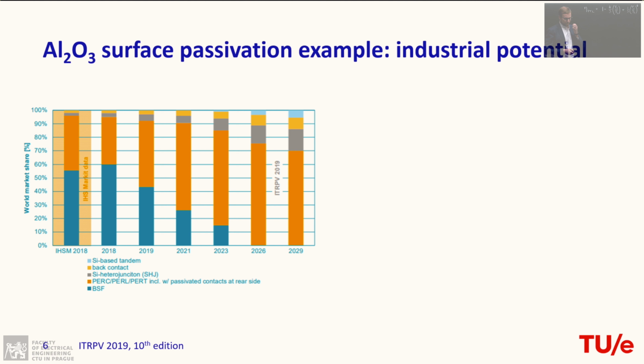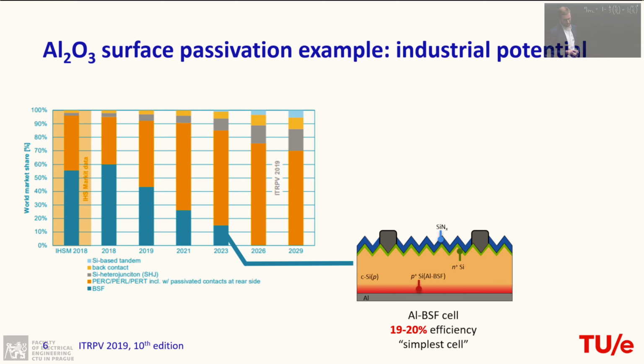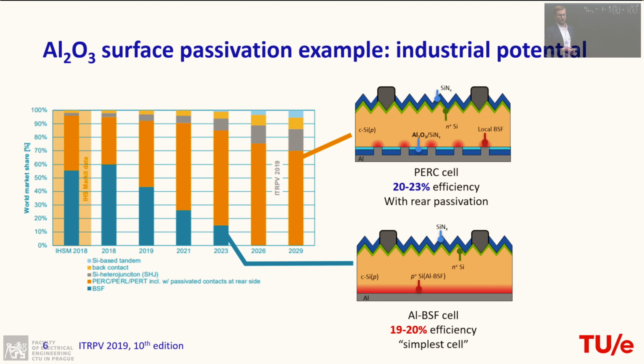Now then, how popular is this now? So here we have the ITRPV roadmap. It shows different types of technologies, so it's a little bit small, but you see that the bulk of the materials here is the picture I showed you before, this aluminum BSF cell. This is the basic solar cell, losing popularity now in favor of the cells that you see in this orange block over here, which are the so-called PERC cells, or passivated emitter rear contact cells. So already here we make use of a passivating contact, you might say. The difference is that we don't have this aluminum basically everywhere over here anymore, but we have now small openings in this material. And in between, you see another material, and that's our passivating material. So you effectively reduce your recombination on the rear side by having this contact configuration. So these are now the most conventional cells that you find in all kinds of modules that you can get for your rooftop. Efficiency is already, let's say, approximately 23% there.